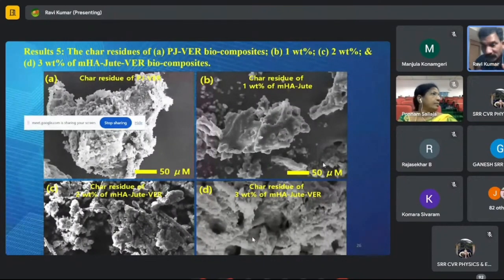It means the char residue is already there, even though we prolongedly heated, some area of the material will be charred. We took that part out and checked the morphology, how the surface is protected with the MHA. From 1% to 3%, it shows very strong protection on the surface of the material. It means our material is commercially viable, and it can also be used for society to stop the catching fire of ceilings or fabrics or whatever it may be.